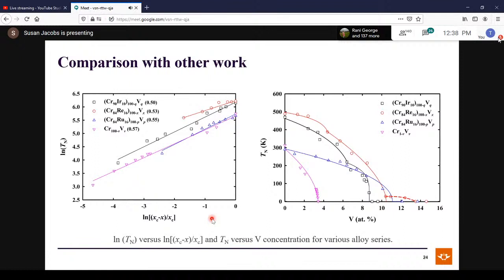Now we compare our work with other work with similar diluents. So the red open circles are a contribution from this work. Here we have a log-log plot of the transition temperature as a function of critical concentration. If log-log plots are a straight line, we know that we can fit a power law through it, and the slopes of these lines are the critical exponents. Now we can see our value is 0.53. There's good correspondence with other reported work of alloys with quantum critical behavior.